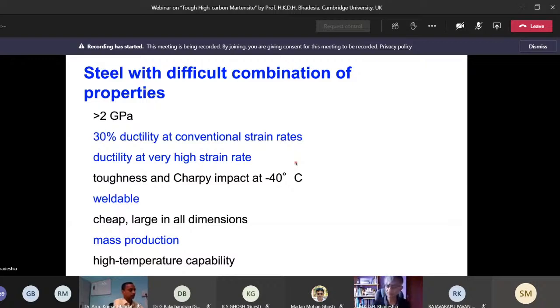We want to design a steel with a very difficult combination of properties. We want a strength which is in excess of 2 gigapascals. That means 2000 megapascals. We want an enormous ductility, okay? 30% ductility at conventional strain rates. And we want a high ductility even at a high strain rate. We want toughness, with Charpy impact at -40 degrees centigrade to be 30 joules. It must be weldable, cheap and large in all dimensions, capable of being mass-produced, and if possible, to have some capability to operate at high temperatures. Now, this is a really nice wish list, okay? But a lot of these parameters that are listed are contradictory. So sometimes you may get weldability, but you may not get the strength.